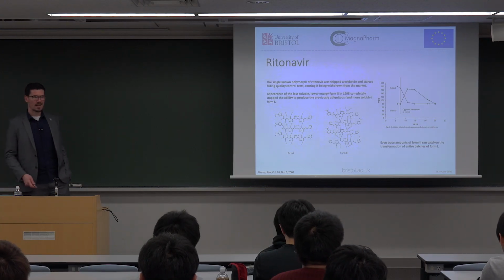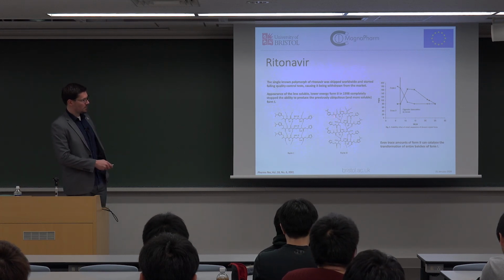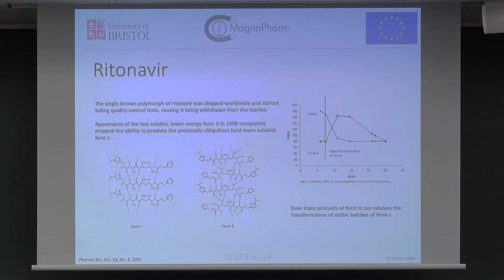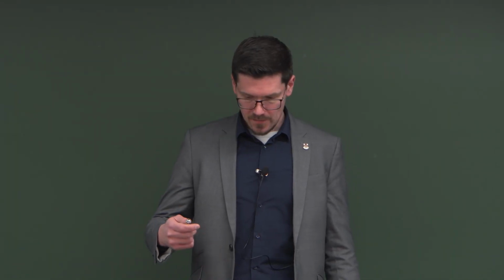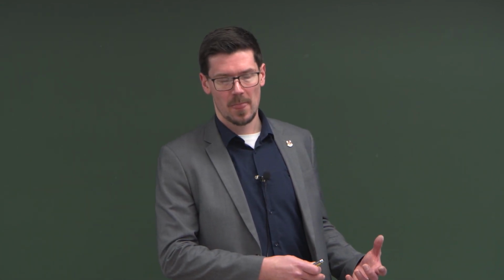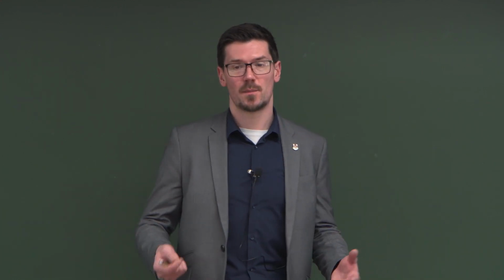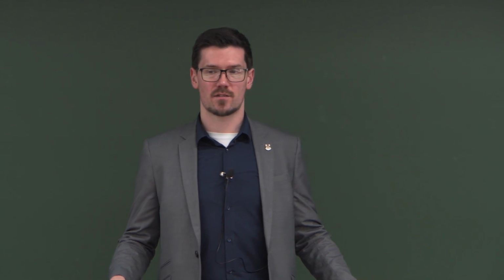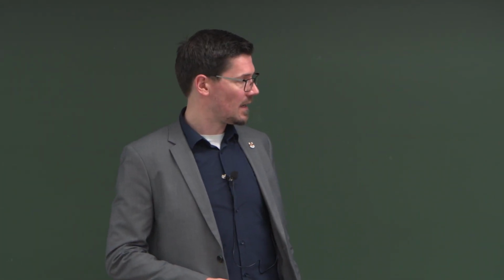What had actually happened was there was a second form of ritonavir, second polymorph, here, Form 2, that they hadn't found. So all of these pills that they distributed around the world were Form 1. People were taking it, it was dissolving, and it was going into the blood and doing its job. The molecule was fine. However, Form 2 appeared, and all of a sudden, it wouldn't dissolve, because how fast it dissolves is exclusively a function of the molecular interactions between these molecules. So basically, it had gone to a more thermodynamically stable form that wouldn't dissolve, completely insoluble. So people were taking it, and it was just going straight through the body and being excreted by the kidneys. Through the gastrointestines.